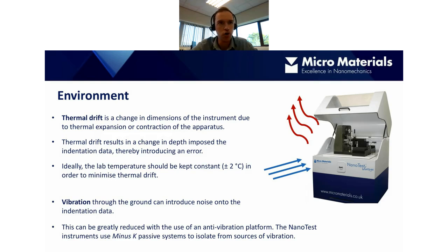So generally speaking, most nano indenters are housed within some sort of chamber or cabinet. So you can see here, this is the Nanotest Vantage, which is the nano indenter that we make here at Micromaterials. And you can see it's housed in this cabinet. So these cabinets can be temperature controlled. For the Nanotest system, if the lab temperature is kept constant within 1 or 2 degrees Celsius, then normally we have very low rates of thermal drift, and so we don't need to worry too much about it.